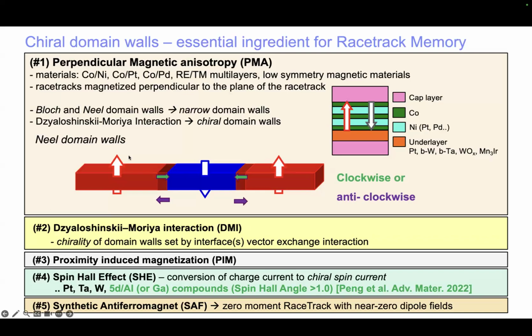So in these domain walls, when we rotate from an up direction, red, to blue, you can see it will rotate in a clockwise direction, or it could be anti-clockwise, depending upon the material. And this means, as we rotate from red to blue, you can see that green arrow, that's the direction of the magnetization in the domain wall. And from blue to red, the green arrow is reversed, because it's a clockwise interaction defined by this Dzyaloshinskii-Moriya interaction, which also makes the domain walls have a certain structure. It's called a Néel wall, in which the magnetization rotates from up to down in a plane perpendicular to the wall as shown here.